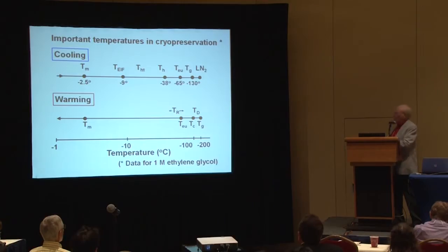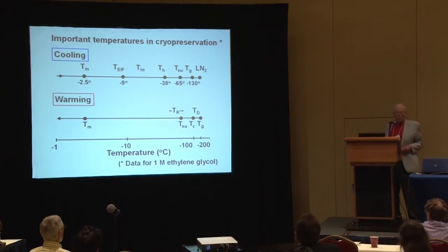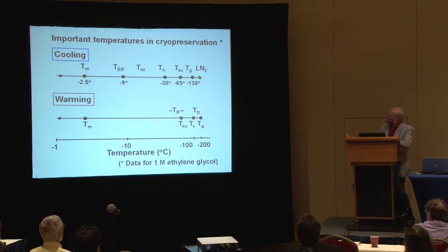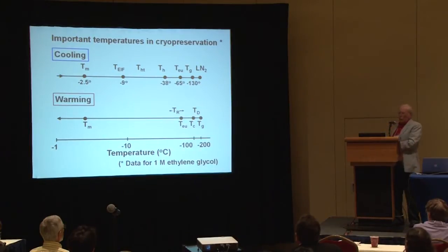Now, the vitreous state can be stable for centuries or even millennia, but it is thermodynamically unstable. Given proper time and temperature, it will convert into the stable form, which of course is ice. So one question is how does one determine what the state of the water is — that is to say whether it's vitrified or whether it's crystallized. I had thought at one time that one could distinguish them calorimetrically, because if it had frozen it would have released the latent heat of fusion, but if it had vitrified there would be basically no heat change.